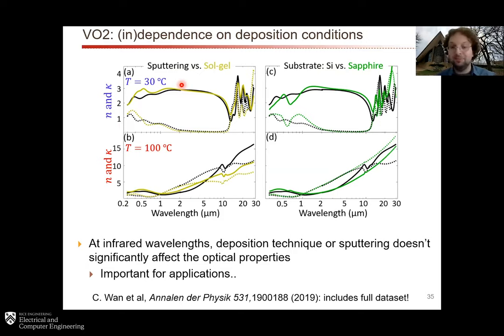You cannot trust somebody else's data set for your own VO2 that you're growing in your lab or using in your lab every time you have a change. And that's because the band structure is very, very sensitive to the deposition conditions and to strain and things like that. And the same thing is true at longer wavelengths than about 11 or 12 microns. And that's because the vibrational features of VO2 are very sensitive, again, to strain and to the substrate and so forth. But there is this magic region between about 2 microns and 11 microns where every curve that we measured is more or less the same, is quite similar.